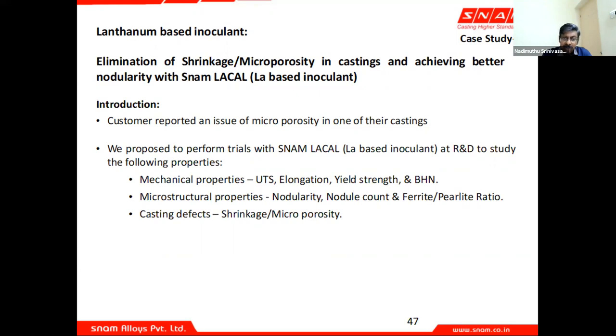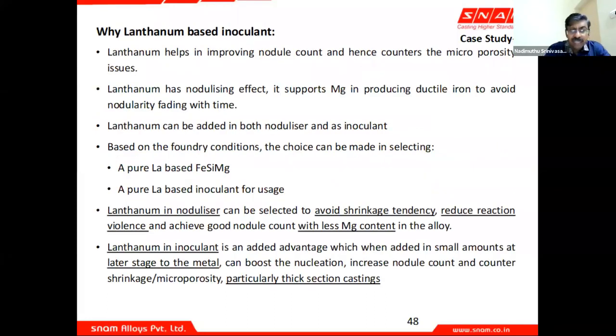The trials were conducted in a similar fashion to what I have told you in all the case studies. Now, why do we use lanthanum? Lanthanum helps in improving the nodule count and hence counters the microporosity issues. It has a nodularizing effect. It supports magnesium. Lanthanum can be added as both a nodularizer and an inoculant. So based on the foundry condition, the choice can be made as a pure lanthanum-based ferrosilicon magnesium or a pure lanthanum-based inoculant for usage. So where do you use the lanthanum-based ferrosilicon magnesium? Where you want to avoid shrinkage tendency and reduce reaction violence. As an inoculant, where you want to tackle any further microporosity arising in a magnesium alloy casting.